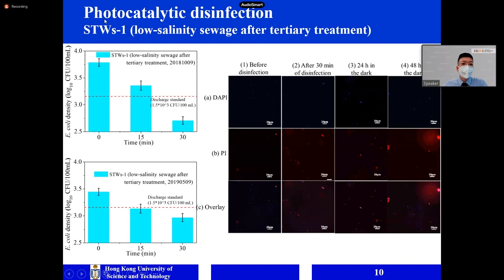For the first wastewater, which is the low salinity sewage after tertiary treatment, we can see that under the simulated solar light, after around 20 to 30 minutes of treatment, it can meet the discharge standard. Then we also ran a duplicate process using this photocatalyst on sewage samples collected at different times.